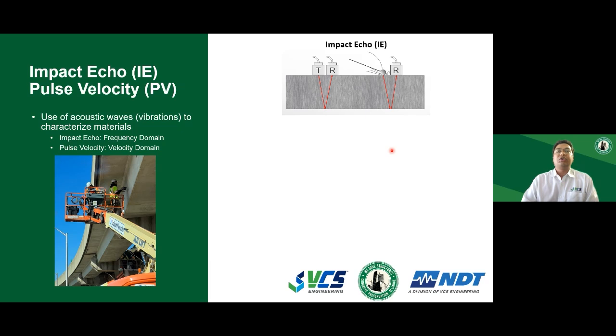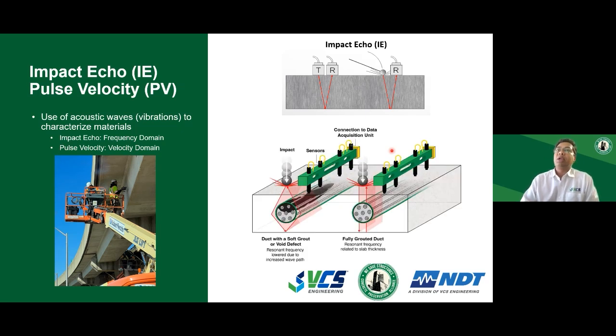Essentially, this technique relies on sending a sound wave or a sound signal, or you can call it a mechanical wave or a stress wave, into the concrete and waiting for the reflections to come back from the back surface and also from the duct surface. Essentially, you place the sensor and you make an impact using a pneumatic impactor. You send the sound waves in. If the duct is completely full of grout, then you will have a quicker reflection. Whereas if you have air void or any voids present in the duct, then it might take a lot longer for the sound wave to come back to the sensors. And this essentially is analyzed in the frequency domain.